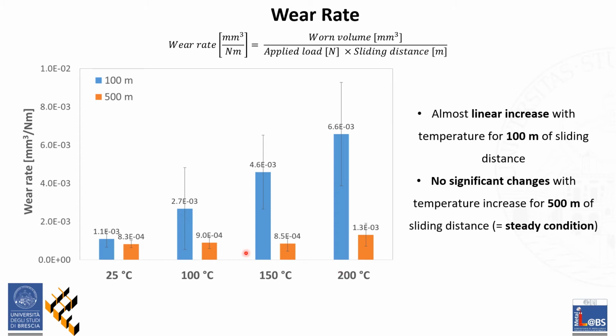A linear increase with temperature can be observed for 100 meters, as a result of the greater material removal promoted by high temperatures. By observing the orange histograms corresponding to 500 meters of sliding distance, it emerges that there are no significant changes as temperature increases. This means that the wear rate is stable with temperature when the steady condition is achieved at 500 meters.